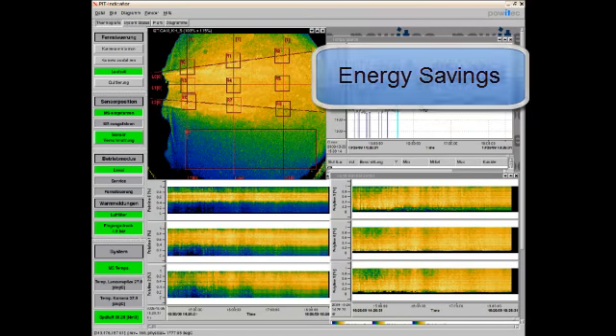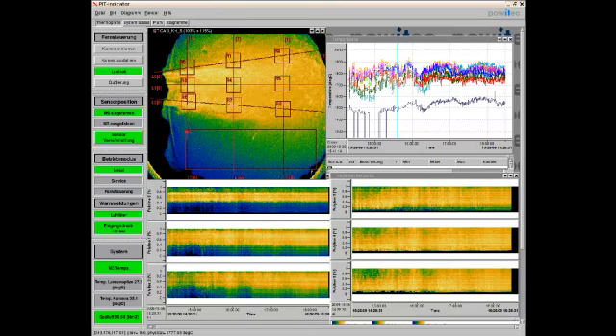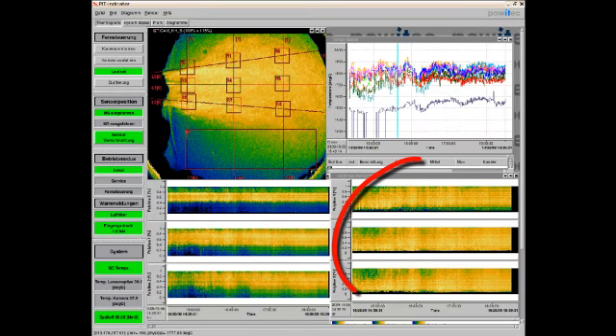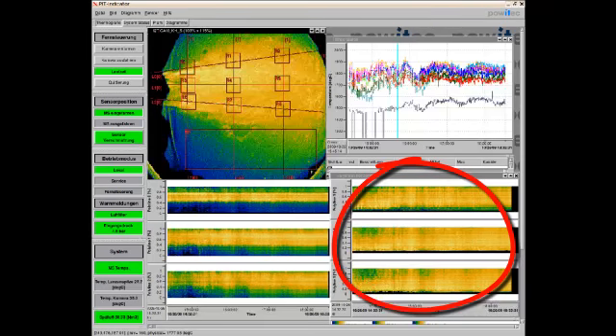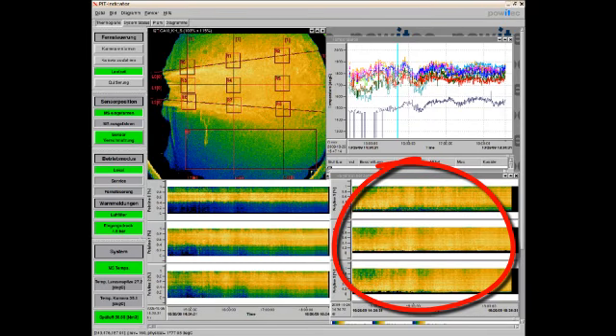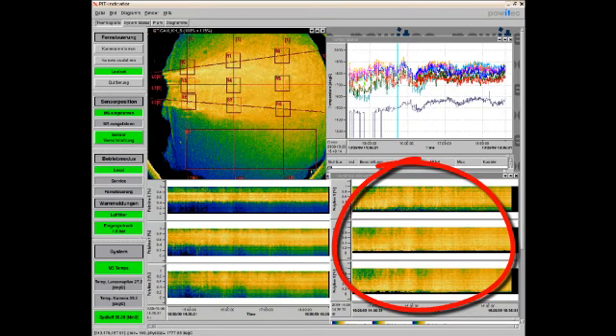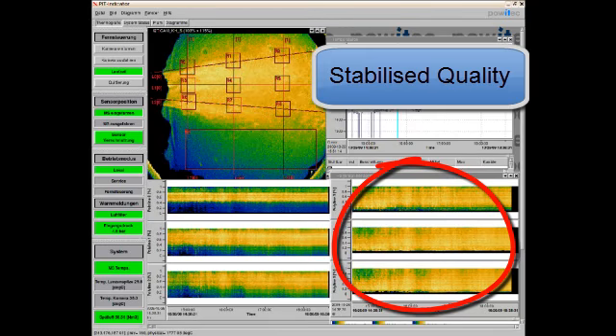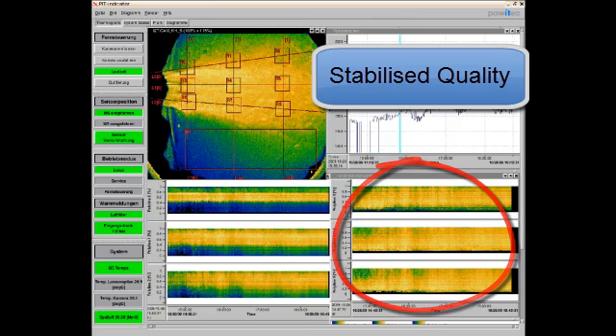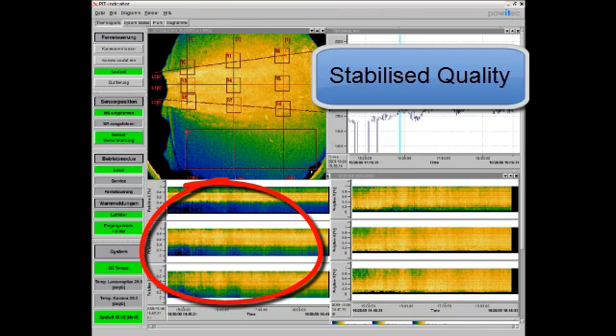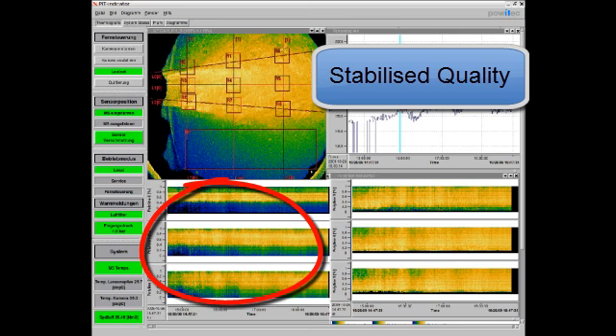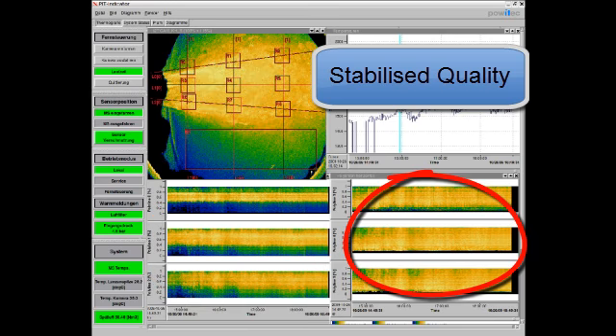Depending on the general process, kiln and burner layout, the sintering process is very sensitive to flame changes. In some plants, very small changes in the flame diameter have a radical effect on the clinker quality. Those plants report that changes in ignition point and thus movements of the sintering zone have been overrated. Changes in flame diameter have more impact on the product quality than changes of the flame ignition point.